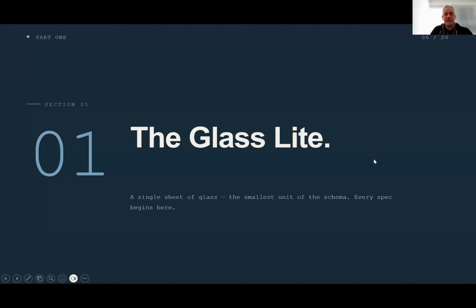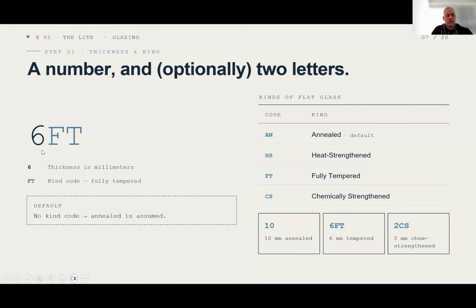So we're going to go through the chunks. The first thing we're going to do is the basis of any glass makeup, which is the glass. The smallest piece in here is the thickness. And sometimes that's enough, because if we don't have a glass type or we don't have a kind, it's by default clear annealed. So just a 6 would be 1/4 inch clear annealed. In this case, we've got 6 fully tempered, so that would be 6 mm clear, fully tempered. We could put annealed if we want to clearly call it out.